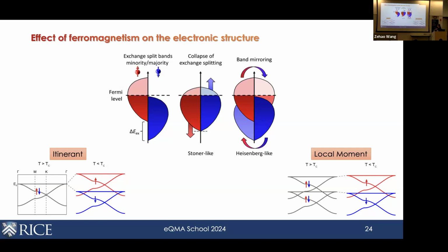They just lose their long-range correlation. Therefore, from an emission perspective, the exchange splitting should still persist across the ordering temperature, except that there's no longer long-range correlation. So the spin polarization should disappear. That's the thing that disappears across the ordering temperature, right? So as you can see, we can very easily distinguish these two pictures if we are able to go across the ordering temperature to examine the evolution of the exchange splitting as a function of temperature.